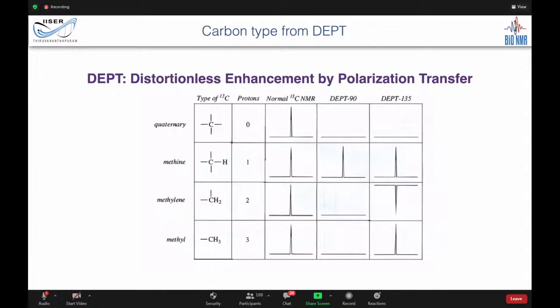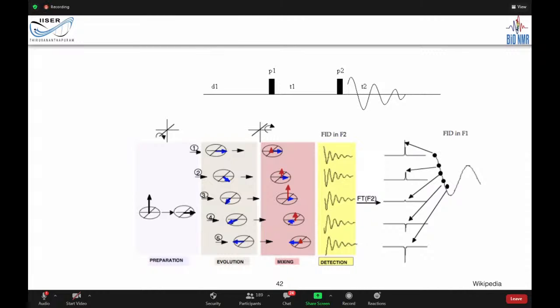Okay, so when it comes to multidimensional NMR, multidimensional NMR is a series of one-dimensional NMR. The only difference is it's a very simple thing. You measure a series of 1D experiments where you vary the distance between these two pulses here. This is a 90-degree and this is a 90-degree. You did it. This is a very simple 2D NMR experiment. If you vary these distances, the difference between each 1D experiment is a delay between P1 and P2. What you get is that the intensity of your signal gets modulated by this delay.